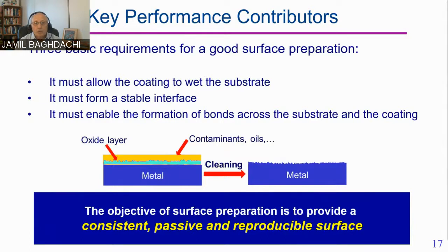And it must also be a stable interface. Like a steel, for example, like iron, if you rub it clean, if you sand it, it's not stable because it begins corroding right away, because corrosion itself is a protective layer on its own. So once you remove that, it's no longer. Aluminum similarly. Shiny aluminum actually corrodes much quicker than the grayish aluminum, because once you remove the white corrosion off of that thing, then it begins corroding much quicker.